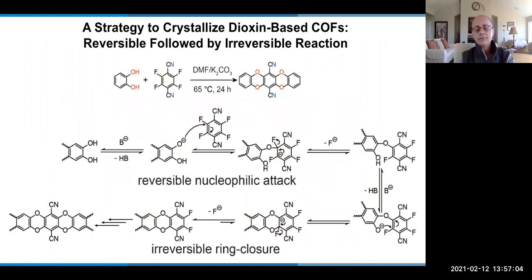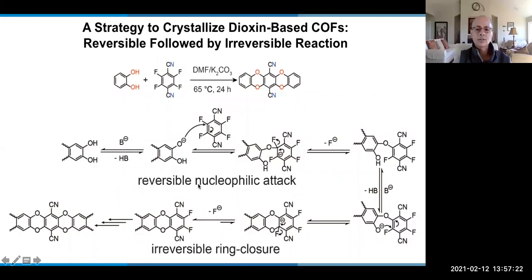Another level of sophistication in COF chemistry is that dioxin is considered to be an irreversible linkage. So how do you actually crystallize that? We look at the mechanism of such reactions, and let's say you have one component of the reaction, the mechanism that is reversible, and that brings the components together so that they have very little chance to move away from each other. And then the last step is an irreversible step. Once those components are close to each other, then you can basically join them because they have no other way of getting away from that linkage.